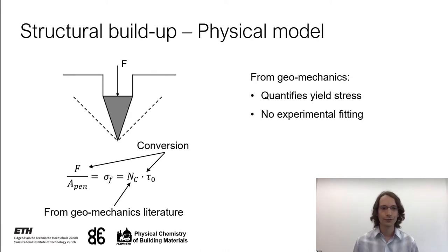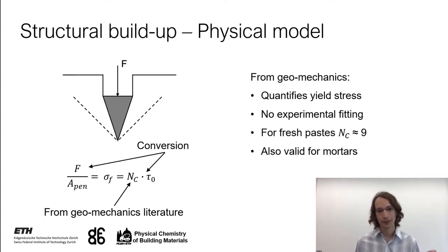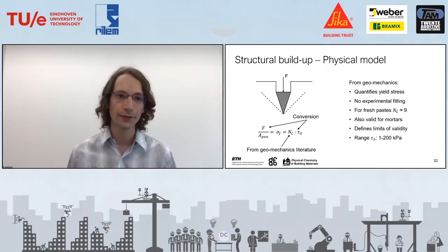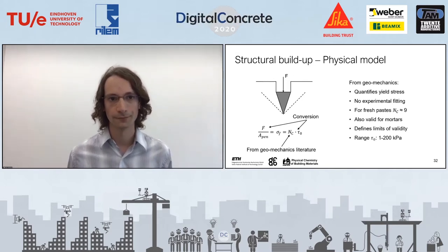The nice approach in this is that now we have a verification from the analytics that we are quantifying the yield stress, and we need no experimental fitting because literature tells us that for fresh pastes and for mortars, this value is approximately 9. And with the framework of this model, we can define limits of validity for this method. So we get a certain range of yield stresses that we can cover.